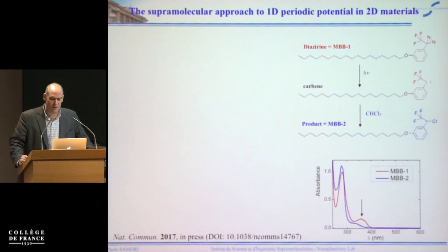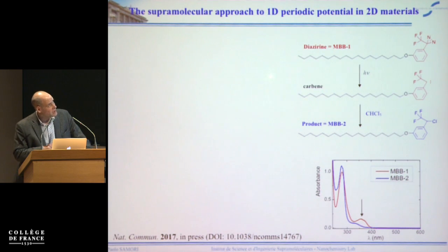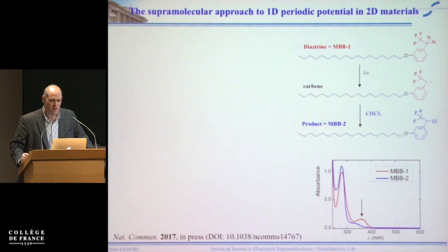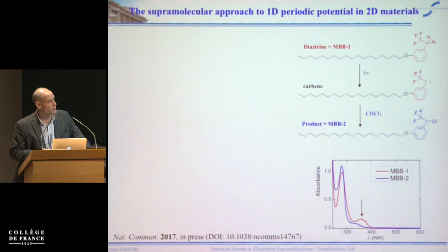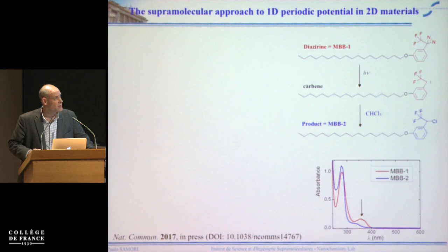Now, what we decided to play with is a molecule that, again, has a very long alkyl chains, because the long alkyl chains for us was a motif in order to create some order, supramolecular structures, so supramolecular lattices on the basal plane of graphene. And then, actually, we start from this diazirine molecule. And this diazirine molecule irradiated with UV light forms carbenes, and in the presence of a chlorinated solvent like chloroform, actually, this creates some products. And the most popular product in our mixture is this one here, okay?